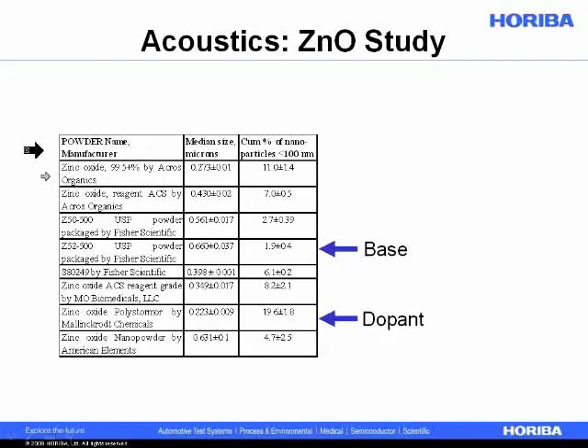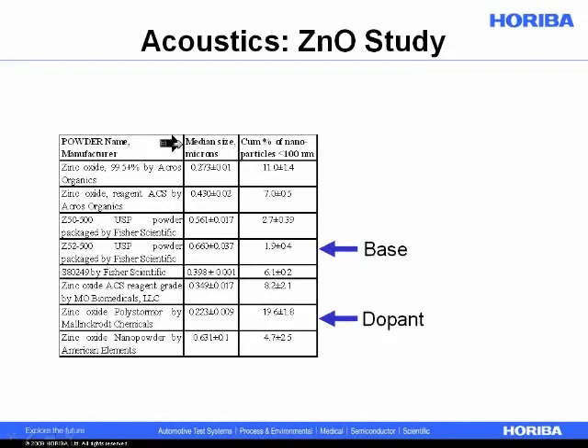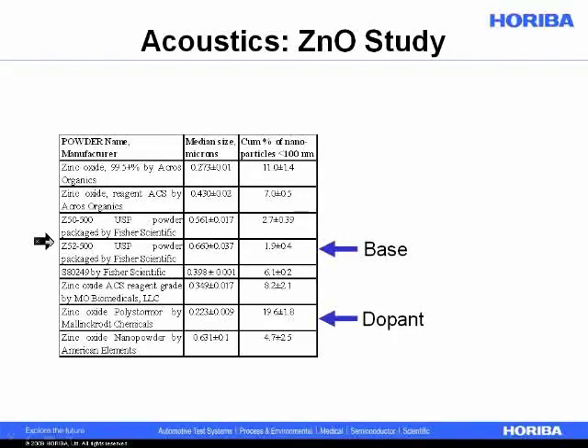In this study, people went out to the market and bought commercially available zinc oxide, reporting the median particle size and the percent of particles below 100 nanometers. One zinc oxide had the largest percent of small particles, and another had the smallest percent. A study was then carried out using the one with fewer small particles as a base and adding some of the smaller particles to the base, making sure the technique was sensitive to the presence of those smaller particles.